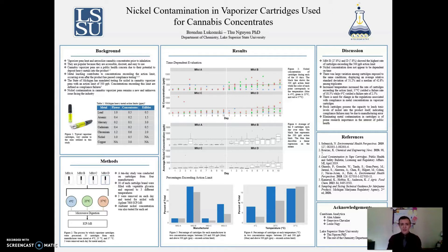The results are quite striking and go to show that there is some manner of metal leaching brought about by these cartridges. In this top plot showing individual cartridge concentrations over time, you can see especially for manufacturers B and D several cartridges above that black 500 parts per billion action limit.